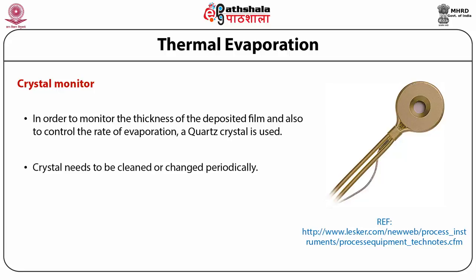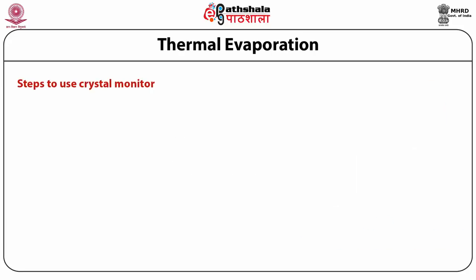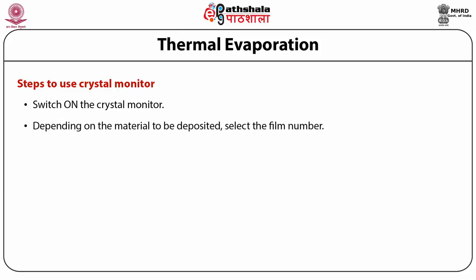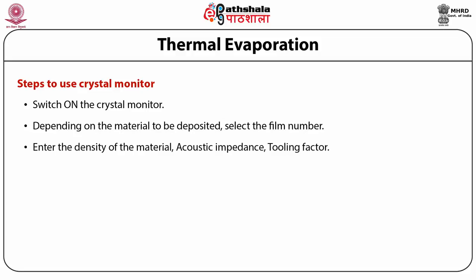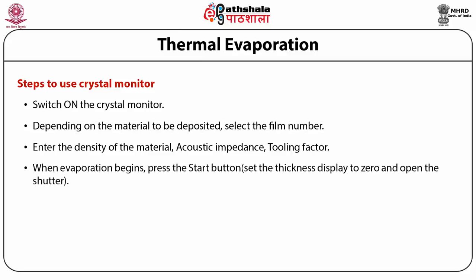Now, the crystal needs to be cleaned or changed periodically. So, there are various steps to use the crystal monitor. First is switch on the crystal monitor. Second, depending on the material to be deposited, select the film number, enter the density of the material, acoustic impedance, tooling factor. Next, when evaporation begins, press the start button, set the thickness display to zero, and open the shutter.